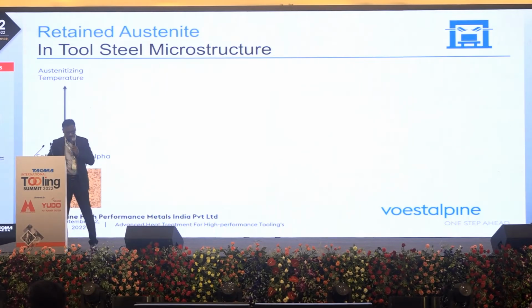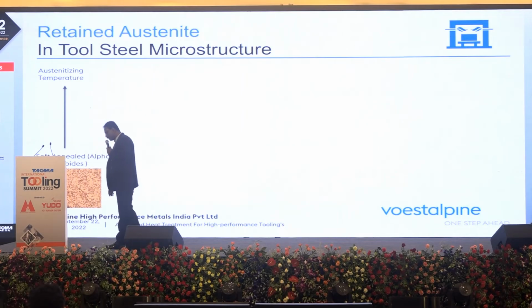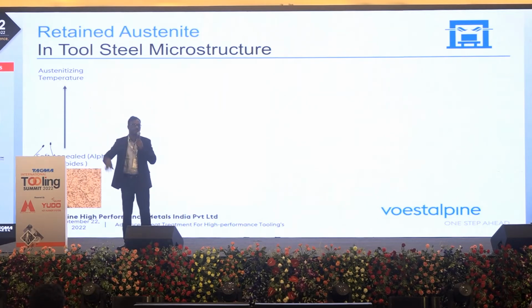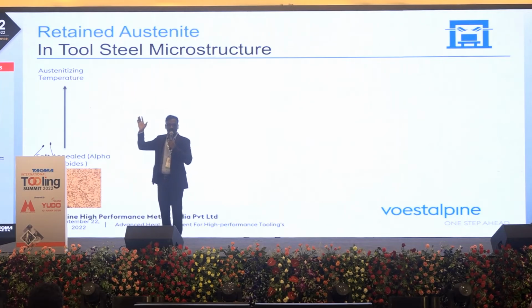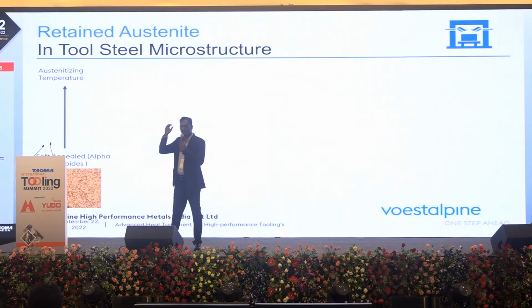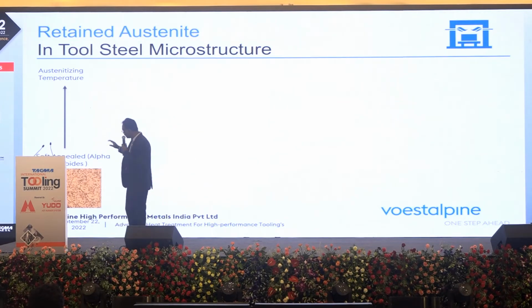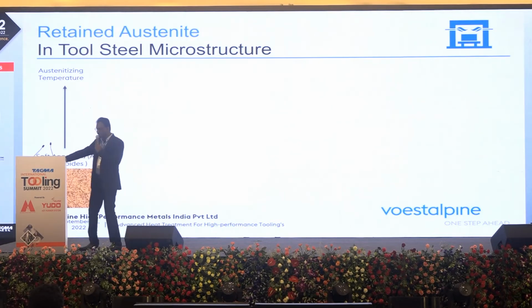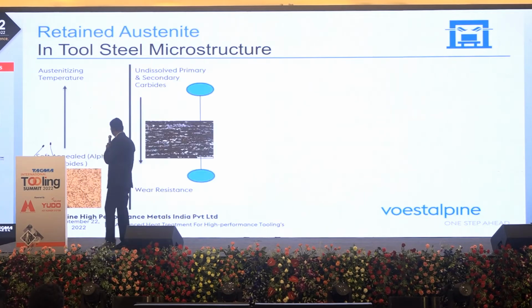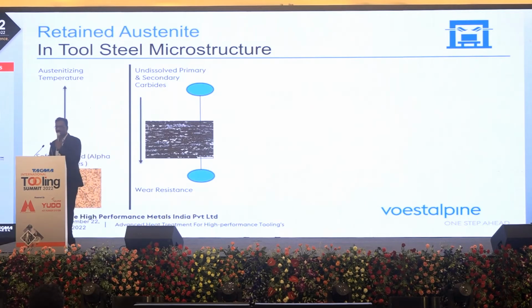If you see on the left, the soft annealed microstructure at the raw material stage is a condition of ferrite plus alloy carbide, mostly belonging to materials with 12%, 15%, 20% alloy carbides. It goes up to high-speed steel. If you see BÖHLER S600, BÖHLER S590, S790, those grades go up to 30% alloy carbides. So with alloy carbides in spheroidized form plus the ferrite matrix, when you take it to the austenitizing temperature, what will happen? The undissolved primary and secondary carbides will be there.